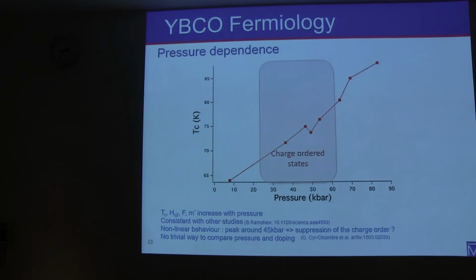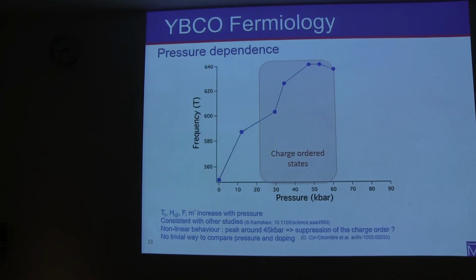And now plotting all of our various data in this plot. I plot here the TC as a function of pressure, so I can measure the TC in our PPMS. For increasing pressures, there is an anomaly here. The critical field measured in our hybrid magnet. Again, there is a region here where it's non-monotonic.